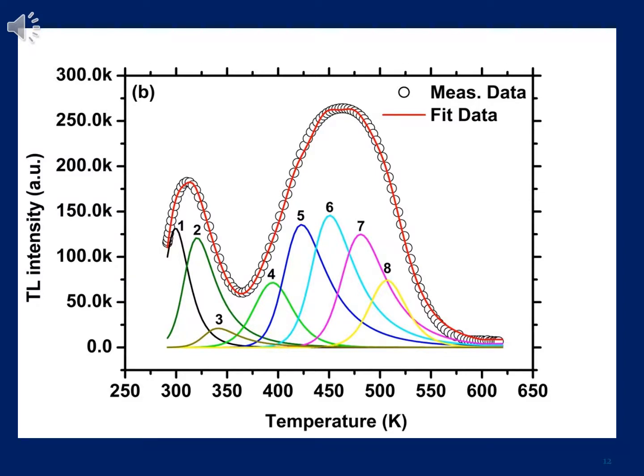Looking at the overall glow curve, the peak is now extended towards lower temperatures. We can see there's a new peak which has been generated, now adding to the previous peak which was measured for a material without a charge compensator. So what is this telling us? We are generating more electron trapping centers which are closer to the conduction band. These are shallow electron trapping centers which participate in the phenomenon of persistent luminescence. Now, this is also proving the effectiveness of charge compensation.